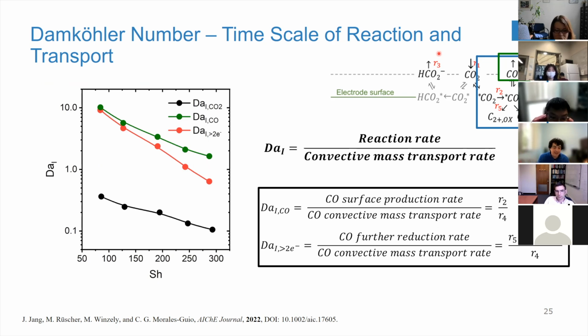that will be the equivalent of rotating at 30,000, 40,000 RPM. What that tells you is that we cannot match the rates of gas diffusion electrodes on a rotating cylinder, but that's not the purpose, obviously. But what we see is that the same first principle model, once you understand the Sherwood number for the mass transfer of CO2 from the gas to the liquid to the solid in a gas diffusion electrode, everything that happens inside of those pores, because you have pores when you deposit the copper catalyst on the gas diffusion electrode, is on the same time scales as what we see in our porous electrodes. So the residence time of that carbon monoxide intermediate inside of the pore is what actually determines the selectivity for the different products that you see. So we can translate the results on a flat polycrystalline cylinder all the way to the gas diffusion electrode, but we cannot reproduce them in the cylinder.